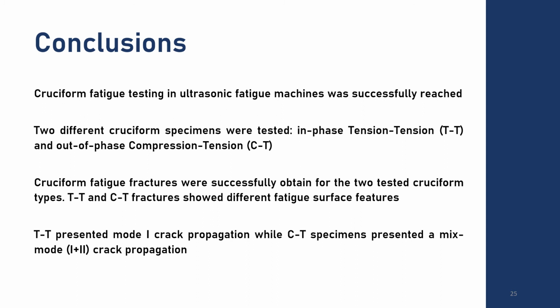Cruciform fatigue testing was successfully reached. Two different cruciform specimens were tested, in-phase tension-tension TT and out-of-phase compression-tension CT. Both types of cruciform specimens achieved fatigue fracture successfully, obtaining completely different fatigue fracture surfaces. The TT presented a mode 1 crack propagation, while the CT specimens presented a mixed mode of 1 and 2 crack propagation, with significant shear damage.